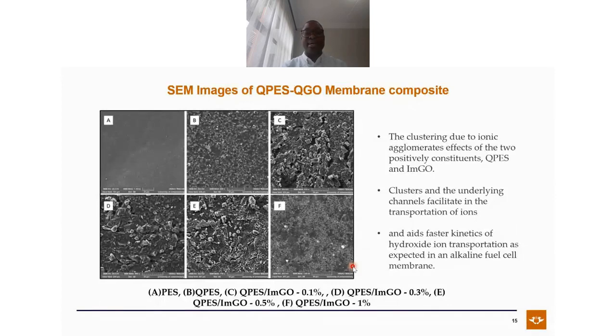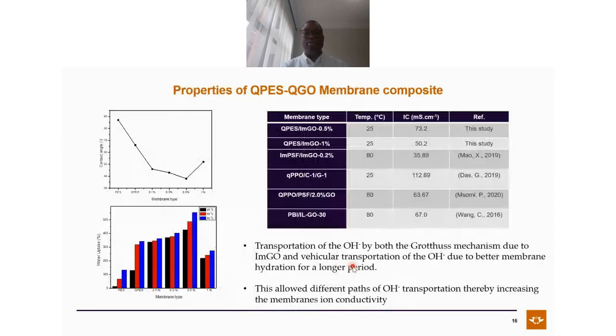And we then expect that the membrane will have, or wouldn't have, higher degradation. We also look at contact angle, we look at water uptake, but the important part I want you guys to see in this slide is the ion conductivity compared to other studies. Again, we did our membrane at 25 degrees. These are the two membranes we tried to show here. We did them at 25 degrees. Then we studied the ion conductivity.